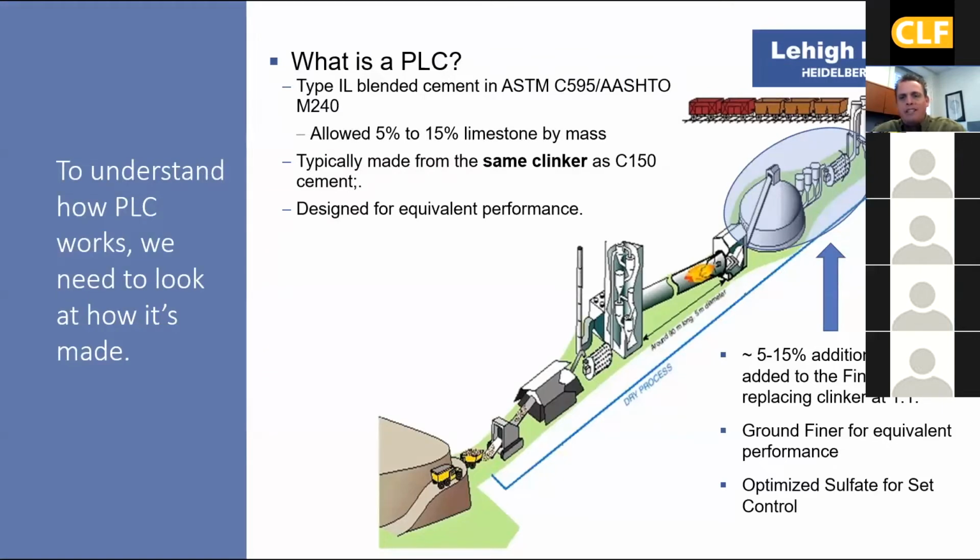The primary sustainability effect of using limestone as an ingredient in blended cements at levels of 5% to 15% by mass is that less clinker has to be produced for an equivalent amount of cement, and therefore less energy is consumed and CO2 emissions and other greenhouse gases are reduced. The properties of Portland limestone cement are equal to or a little better than regular Portland cement.